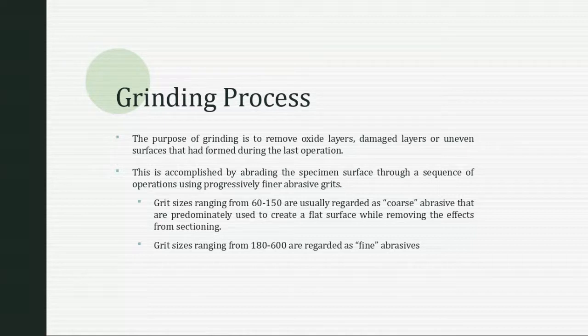There are two different types of grinding categories. The first is coarse abrasive, with grit sizes ranging anywhere between 60 to 150 grit. Then you have the fine abrasives, which are in the range of 180 to 600 grit. I'll get to their micron sizes shortly when I show you guys the chart.